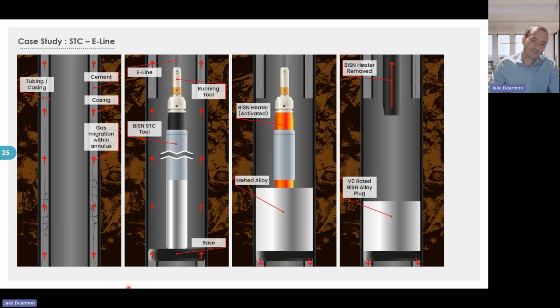We'd go in and underream that clean. We would then set a base for the base of the bismuth plug. Sometimes that would be a cast iron bridge plug inside the rat hole down here. Sometimes that would be an annular or an inflatable up inside the section mill window. We did a good mixture of both. You then go in with an E-line tool down to depth. We would activate that heater and then remove that heater from the molten plug anywhere from 15 to 20 minutes after activation. So pretty quick burn cycle there. And then remove that heater out.